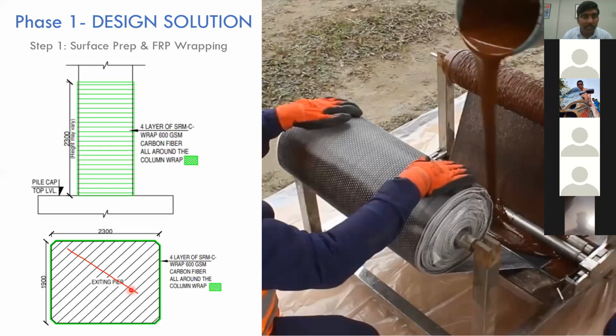All right, so you have this column, you have this pier. Basically, we are increasing the shear strength. Okay, so we have this fiber. It is unidirectional. Along the length of the roll, you have the fibers. So this is the direction. Green shows the direction of fibers. Okay, as per calculation, 4 layers of this 600 GSM carbon fiber was found sufficient for compensating the deficiency.